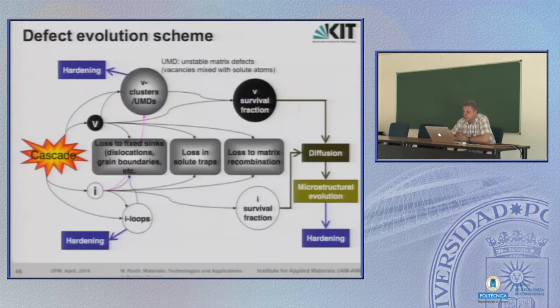Here is a scheme which describes it in one view, I hope, but nevertheless, let's go through it. We start with a cascade producing these large numbers of defects, namely interstitials and vacancies. Then what happens to these vacancies and interstitials? Due to interaction with the dislocations and grain boundaries, but also due to solute atoms in the lattice and due to simple recombination, they go away. It's a recombination process due to several reasons. Then vacancies and interstitials are canceling each other out, so they are gone.